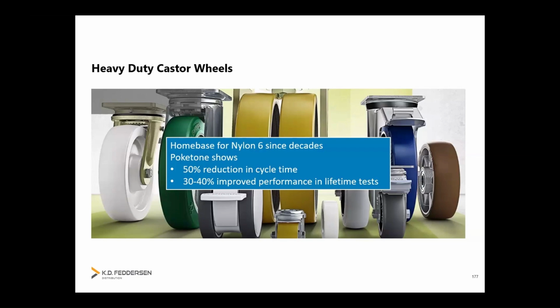But this was not the major driver for the customer. The driver was the mechanical properties that they had been testing with this application. That means all the lifetime testing, the fuse test, maximum stress test, maximum load test, bowler fatigue, and everything else, all the long-term testing that they have done. And there they found, depending on the test, an improvement of 30 to 40% over the nylon material that they have been using since decades. So now they are stepping in and have replaced the heavy-duty caster wheels with polyketone. And this application will be multiplied.